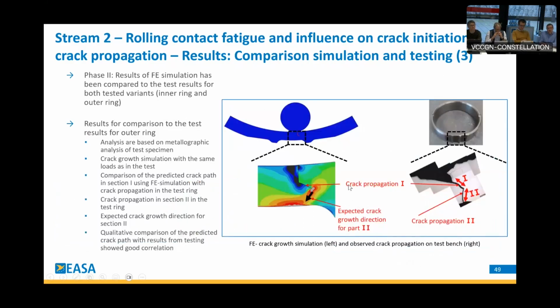Coming to the ring, to the sample here with the notch. Again, the analysis is also based on metallographic analysis of the test specimen. The crack growth simulation has seen, of course, the same loads as in the test, as is done also for the other comparisons. The comparison of the predicted crack path using the FE simulation was done, and we expected at the end a certain crack growth.